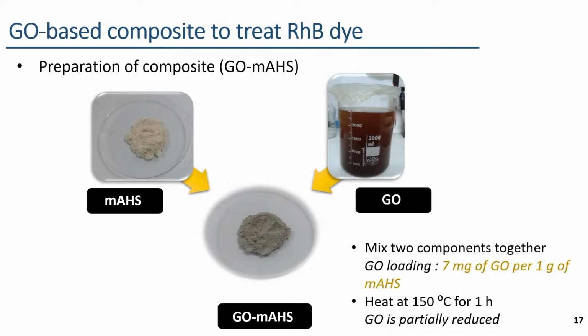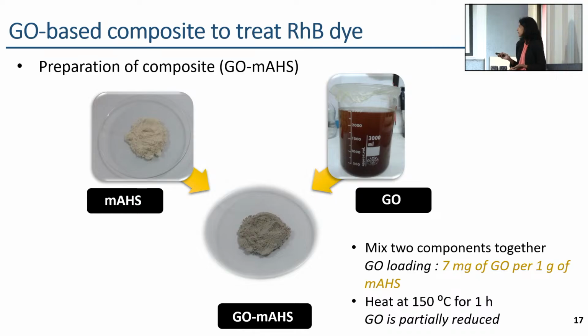partially reduced graphene oxide. For this GO-based composite preparation, I have used the 12-hour synthesized GO sample, that is GO12, because based on the results of the structural variation study, we could see that the RGO12 sample has high methylene blue adsorption, indicating a larger graphitic basal plane. Therefore, I have used the GO12 graphene oxide sample to get a high surface area, or the larger graphitic basal plane, with this partially reduced graphene.